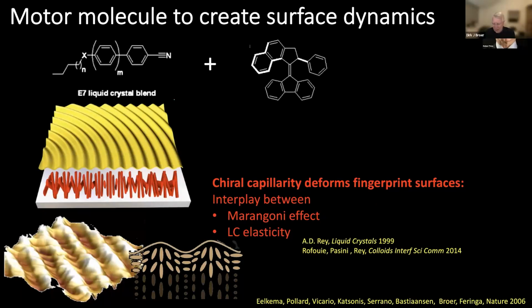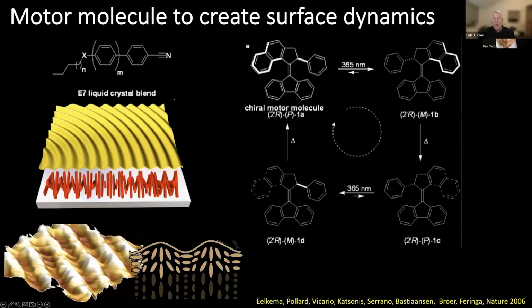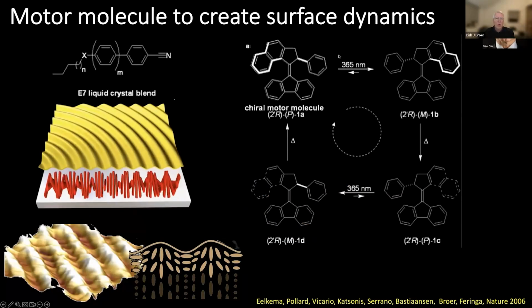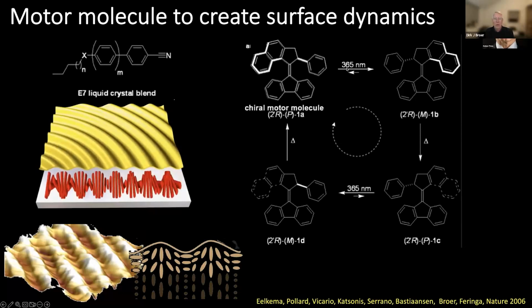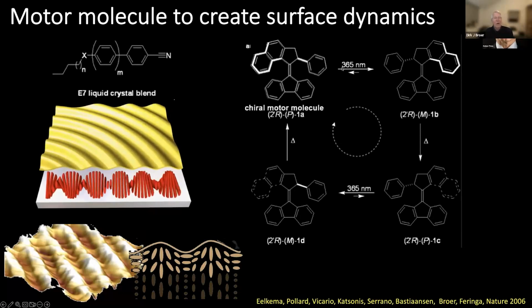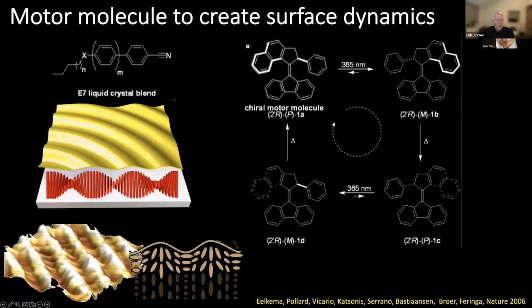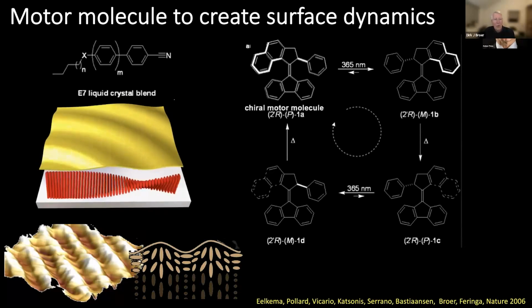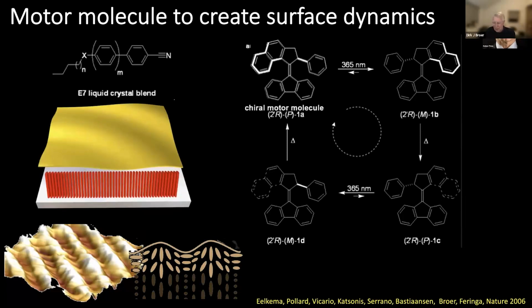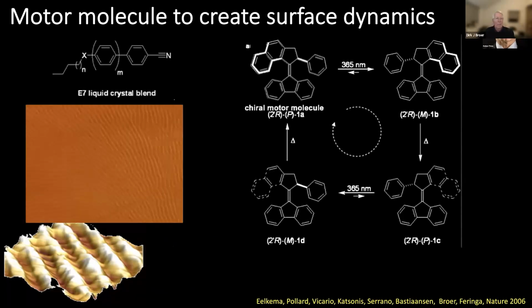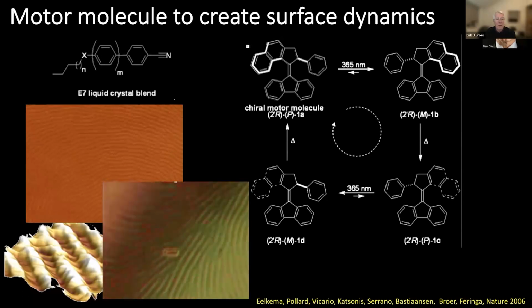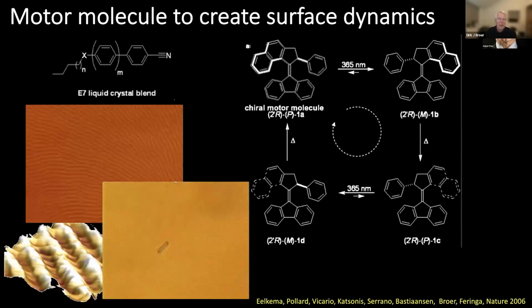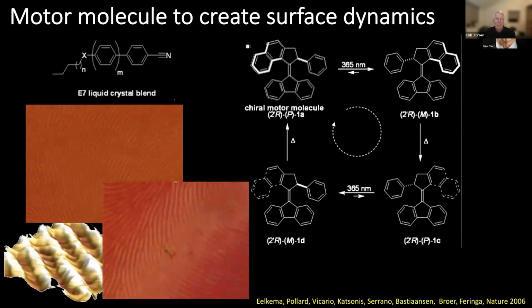But of course, we still have now the motor molecule of Ben in the system. And as soon as we start to expose this with light, the molecules tend to go from one enantiomeric form into the other enantiomeric form, and that makes the pitch of the helices start to unwind, the pitch becomes larger. And because of that, the fingerprint texture starts to rotate over the surface. And when you add a little fiber element to that, it tends to rotate with the fingerprints as well.